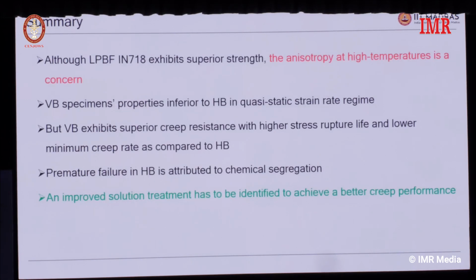To summarize this part, the VB specimen so far seems to be good, and the premature failure in the horizontal build is attributed to a kind of chemical segregation. What it means is that unless we employ a certain amount of heat treatment, it's not easy to get the properties we are looking for with additively manufactured material.